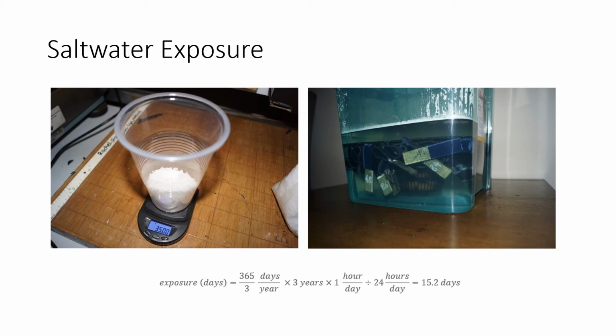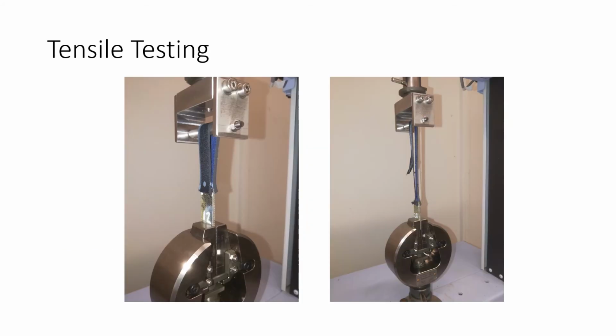A salinity of 35 grams of salt per litre of water was used to model the ocean's salinity. The samples were exposed for 15 days, which modelled 3 years of exposure if the wetsuit was used every third day for an hour at a time. Both the exposed and unexposed samples were tensile tested to determine their strength characteristics. 3 samples for each substrate and adhesive combination were tested.